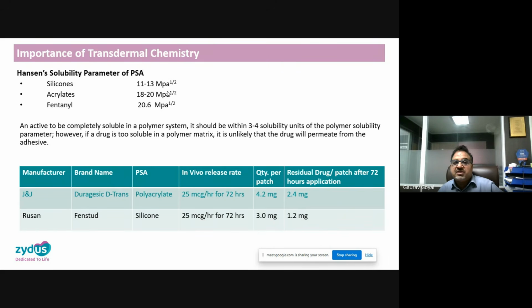So therefore, if you see the examples below, if we make it with a polyacrylate adhesive, we need to load the drug very high. It is almost 4.2 milligram of drug we need to incorporate into the patch to get the in vivo release of 25 microgram per hour for 72 hours. It is a 3-day patch. 72 hours means 3 days. So the drug release rate is 25 microgram per hour. To get this particular drug delivery from the patch system, we generally need to incorporate 4.2 milligram